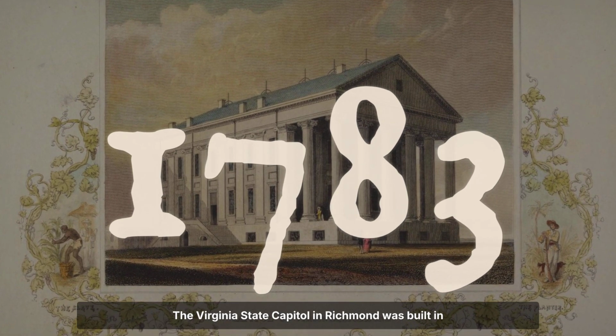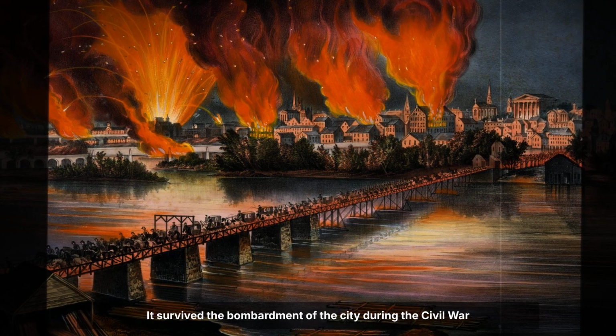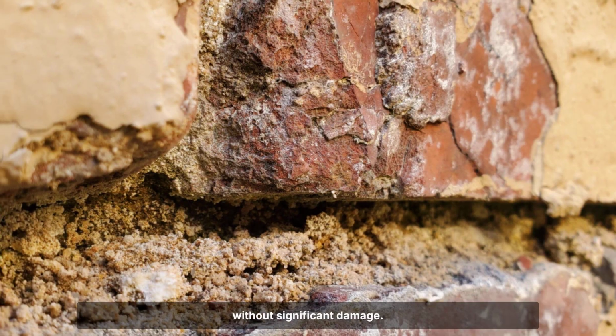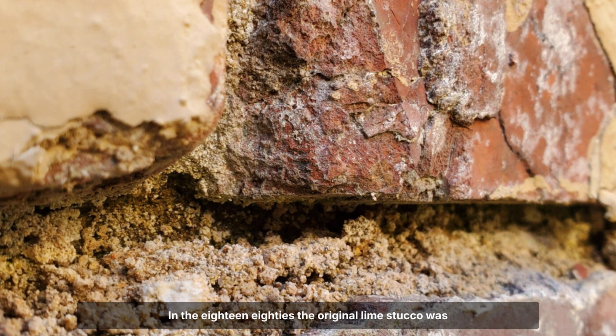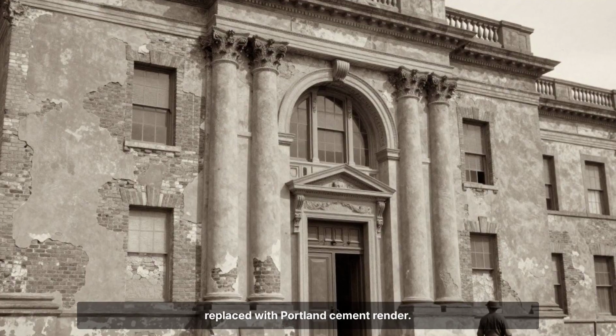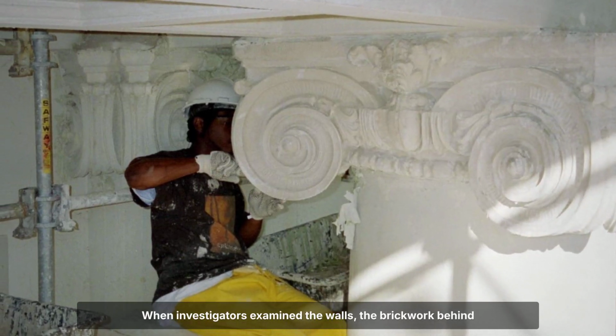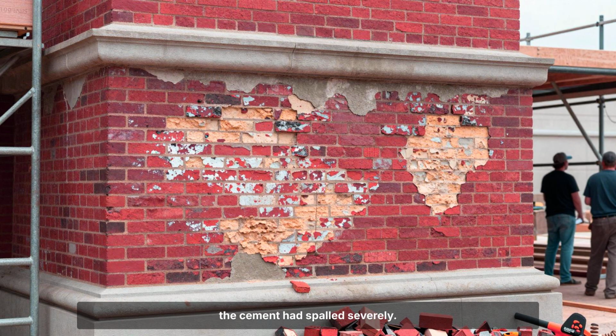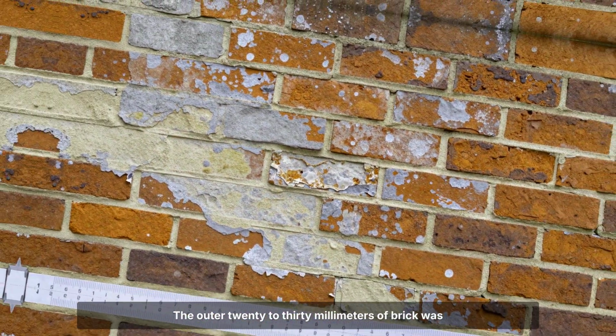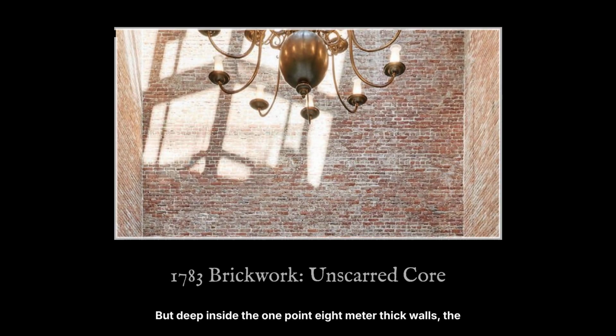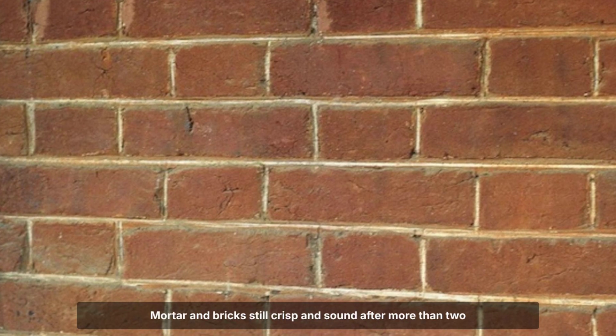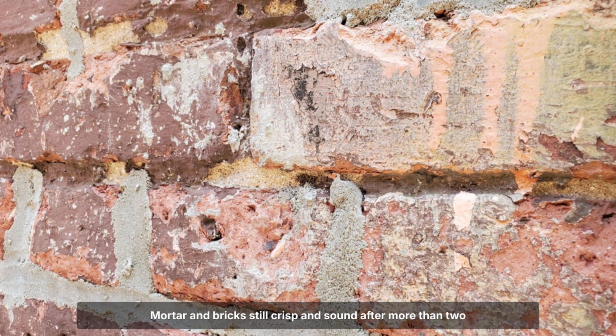The Virginia State Capitol in Richmond was built in 1783. It survived the bombardment of the city during the Civil War without significant damage. In the 1880s, the original lime stucco was replaced with Portland cement render. When investigators examined the walls, the brickwork behind the cement had spalled severely. The outer 20 to 30 millimeters of brick was crumbling or still attached to the cement when it was pulled away. But deep inside the 1.8 meter thick walls, the brickwork was pristine. Mortar and brick still crisp and sound after more than 200 years.